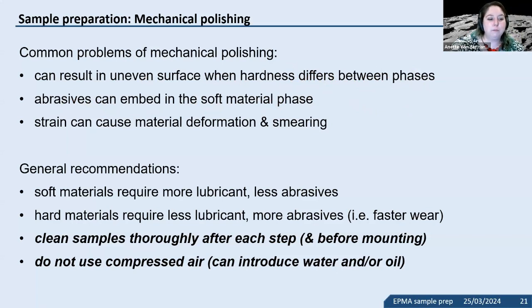You can reduce that by thoroughly cleaning your materials after each step, specifically with an ultrasonic bath. Yeah, it's just something to keep in mind. And then usually soft materials require more lubricants and less abrasives, whereas hard materials require less lubricants and more abrasives.